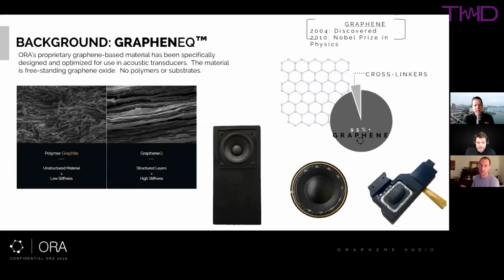Okay. But what we're doing actually, because it's graphene oxide, allows us to take smaller flakes. So each one of these layers isn't continuous. But based on the aspect ratio of these flakes, they're almost vanishingly thin, but they have some sort of XY dimension, and they want to lay flat. So in the deposition process, they naturally tend to stack and lay flat on top of each other. And then the cross-linking agent creates a reaction that holds them in that position.